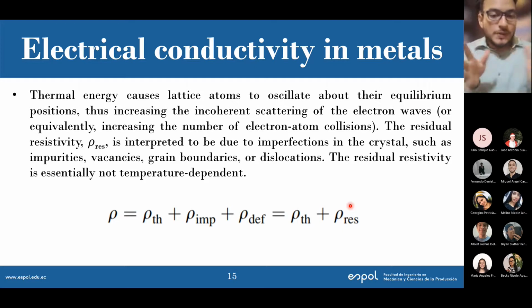In general, we can say that the resistivity is composed of two main terms: a residual resistivity that comes from imperfections in the crystal and is not temperature dependent, and a thermal term that comes from thermal energy. This formula is actually known as Matthiessen's rule. It's just a rule that says resistivity is equal to the addition of different resistivities. All of these are independent scattering processes, and they are additive. That's what Matthiessen discovered, and it's nothing extraordinary, I believe. It's just adding different and independent scattering processes, considering, remember, electrons as waves, and that's why we consider it scattering of waves.